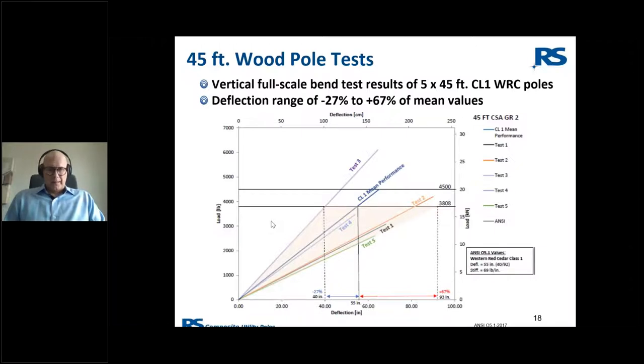The other four poles in the test, however, deflected more than the mean performance would have predicted, and three of them didn't even make the factored class load here, and test two landed, looks like somewhere around 4,200 pounds of load. And test five, opposite to test three, was the most deflecting wood pole, if you will, which failed, it looks about 2,500 pounds. And if you carried that on through to class load, it would have been plus 67% of the mean performance value.